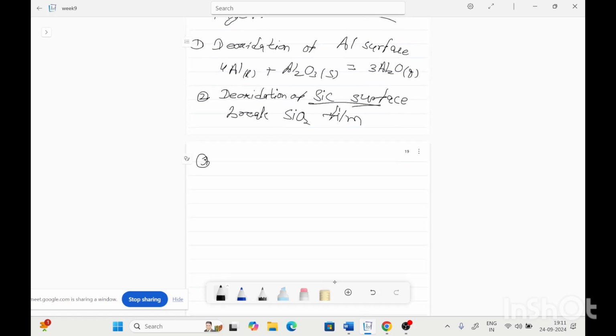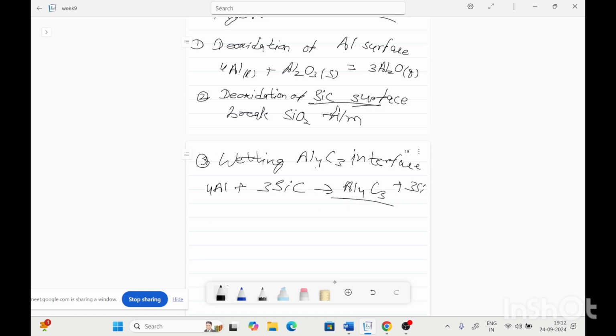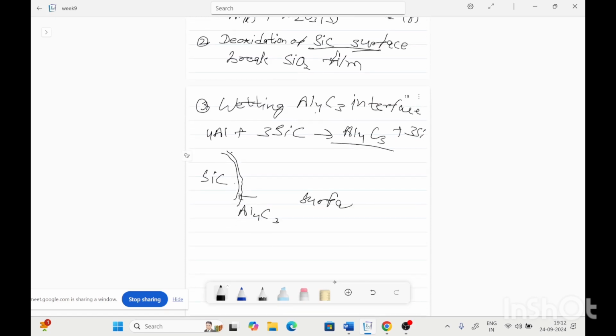And the third is the wetting through the Al4C3 interface. Means the Al4C3 compound forms during this reaction that leads to good wetting. Aluminium plus 3 silicon carbide forms the Al4C3 plus 3 silicon. So the Al4C3 layer deposits on the silicon carbide and alters the surface tension of the silicon carbide surface. Means this surface is the Al4C3. So this alters the surface tension and surface energy that leads to decrease in contact angle.